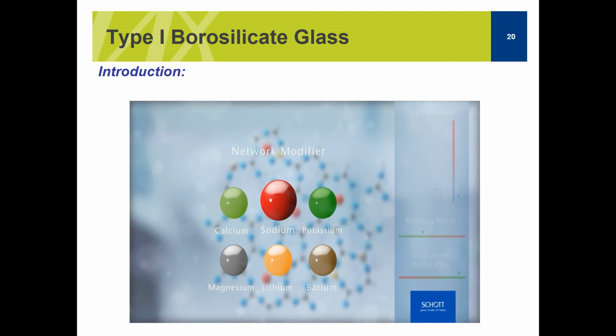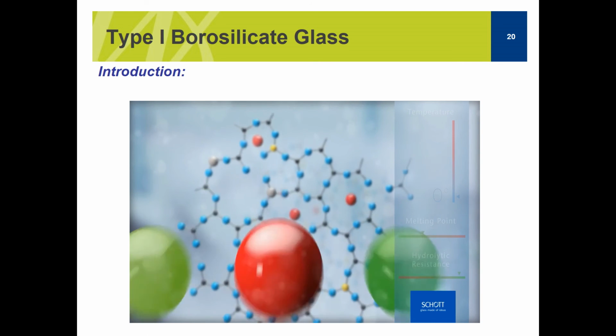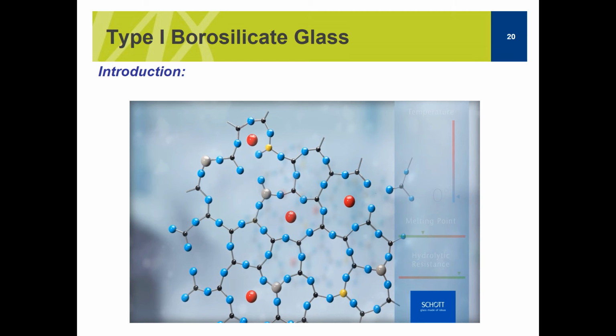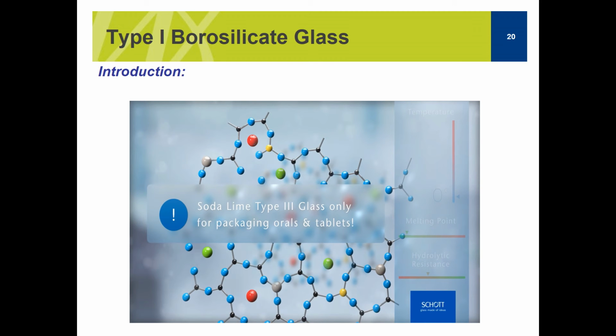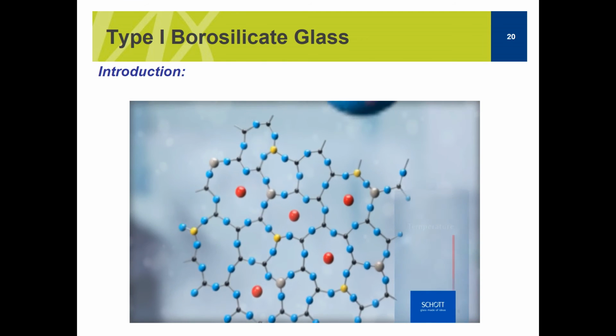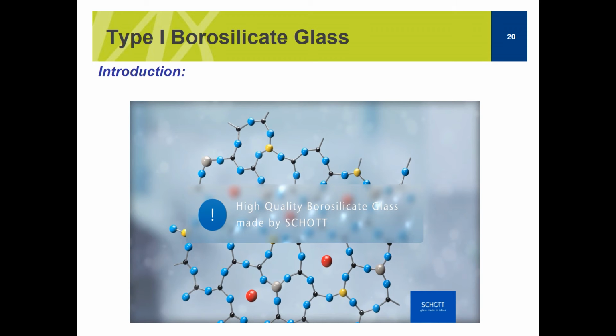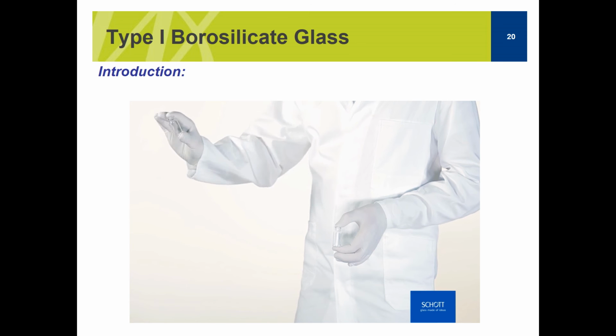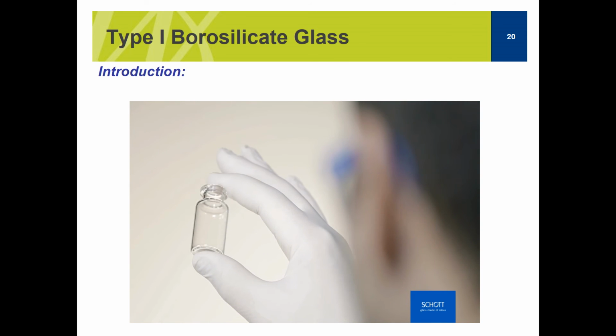The quantity and the ratio of network modifiers in the structure determine many of the chemical and physical properties. If, for example, more calcium is added to the glass, the melting temperature of the glass is decreased again, and in turn, the hydrolytic resistance is also decreased again. This structure shows a soda-lime type 3 glass, which is only recommended for packaging oral solutions and tablets, but not injectable liquids. In general, the higher the hydrolytic resistance of the glass, the higher the quality of the glass, as there is less risk of interactions with the drug formulation. The quote from Schott's founder, Dr. Otto Schott, "Glass is not just a pure coincidence," is today even more relevant than ever. Schott. Glass.